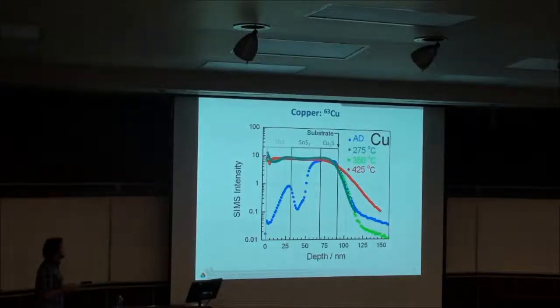So what we learned from this is, as deposited case, this is annealing temperatures, which I just mentioned. For all the next slides, you will see that all the layers are heavily diffused, which means basically there are almost no interfaces between the metal sulfide binaries. You can easily see that these gray boxes show the prescribed morphology that one would expect by doing X-ray reflectivity and recalculating it purely in thicknesses of the metal sulfide binaries, assuming that the metal sulfide binaries should be nanolaminate, okay?